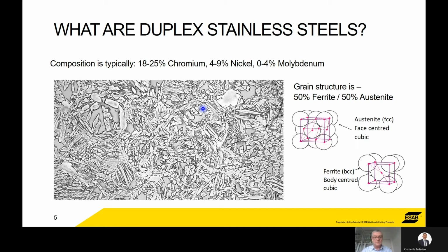And this combination, the resultant combination of austenite and ferrite, creates a fantastic material that is very corrosion resistant and is very strong. So the tensile strength is very much better than, say, a standard stainless steel. Okay. What you see here under a microscope, a picture of duplex stainless steel. The white areas are austenite and the black lines around them are the ferrite. So what we have is a 50-50 ferrite austenite balance.